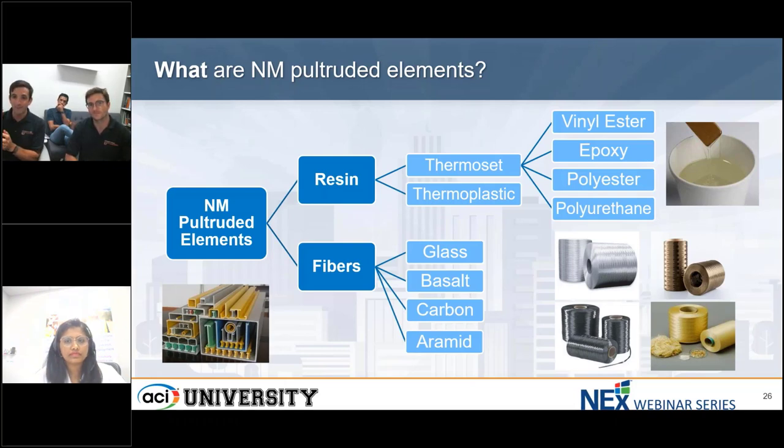So you talked about compatibility — we have a question about long-term fatigue. How do pultruded non-metallic shapes perform in resisting long-term fatigue, and how do their fatigue characteristics compare with other materials? The resin protects and transfers the load, and it's the fibers primarily that determine how it performs from a fatigue standpoint. Carbon versus glass are very different products. More than fatigue, you also have creep — fatigue is multiple load cycles on and off. Similar to steel, carbon and steel perform at a similar fatigue level. Glass does suffer also from fatigue and creep rupture, which is sustained load over a prolonged period of time.